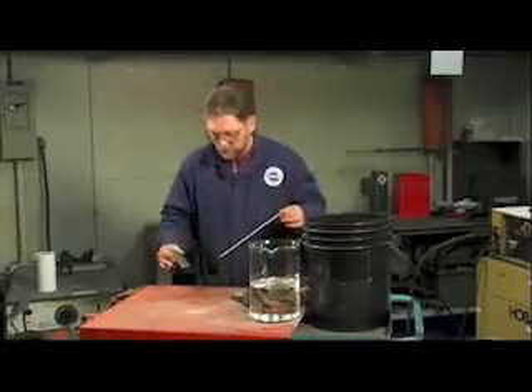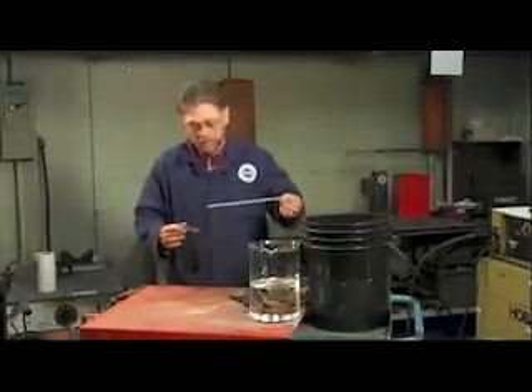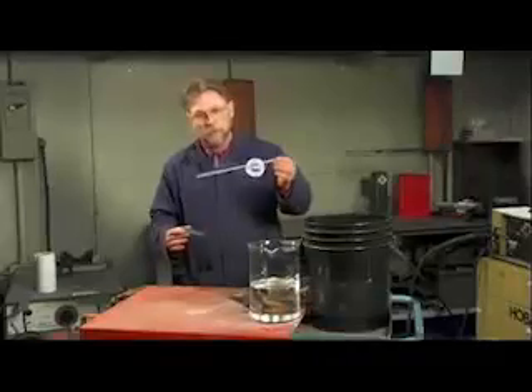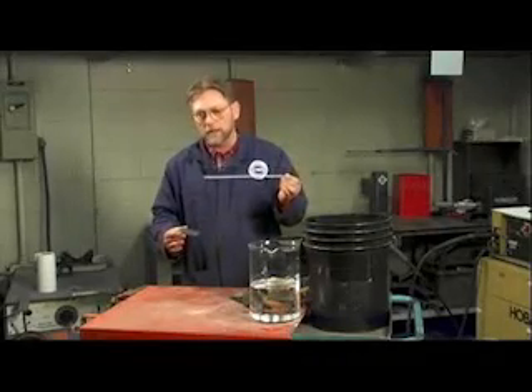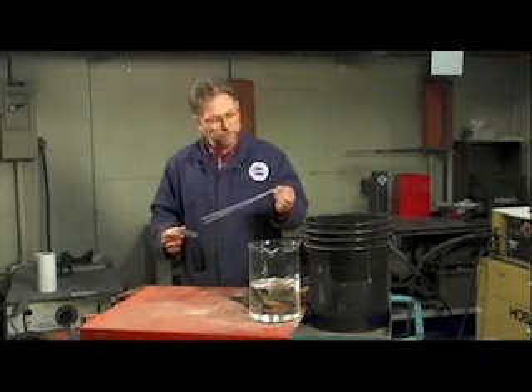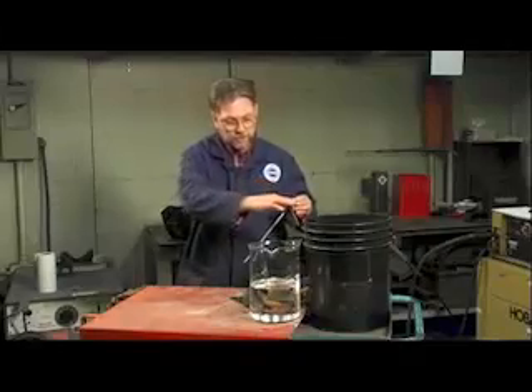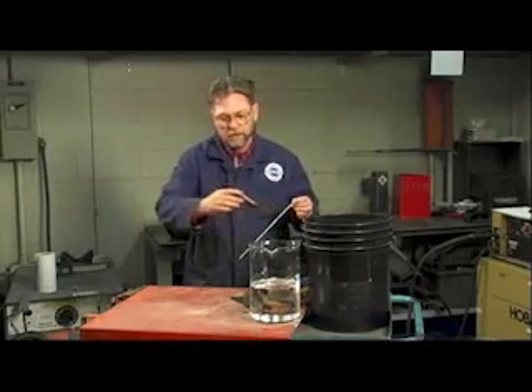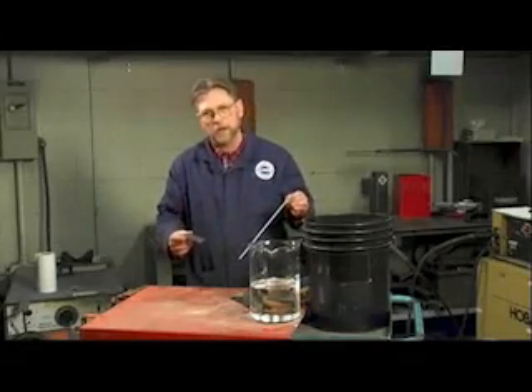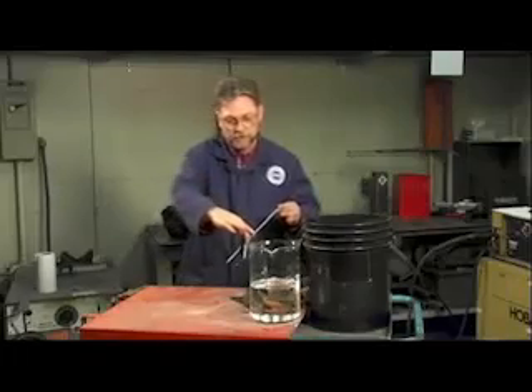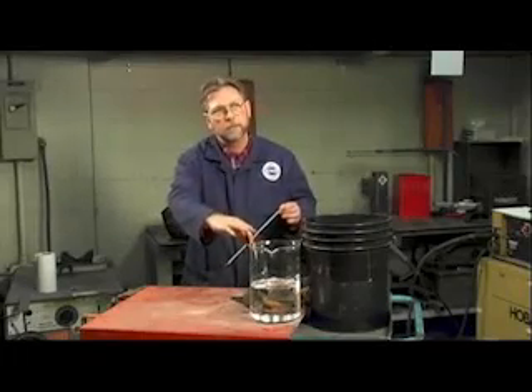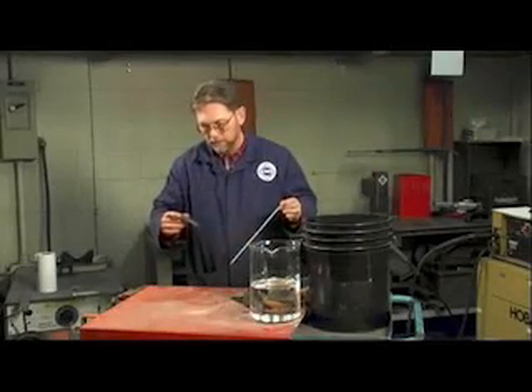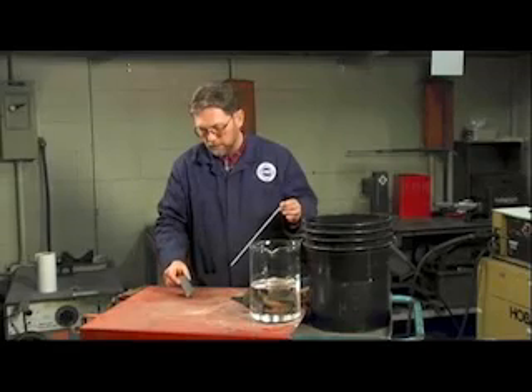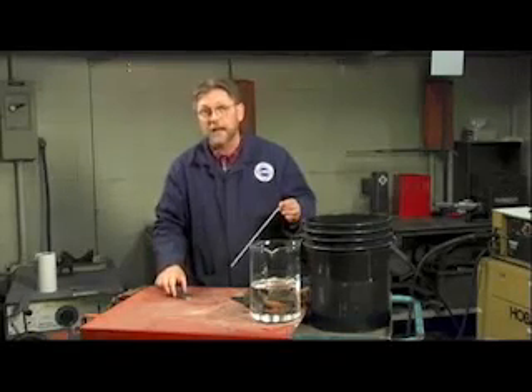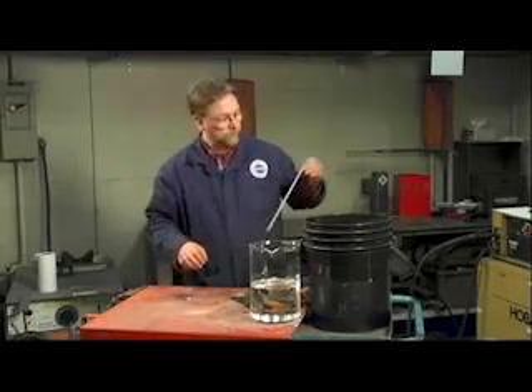So what we're going to do now is make a weld bead on the surface of this piece of plate using a 2.4 millimeter diameter low hydrogen electrode. We're going to quench it into some cold water and then dry it off, chip the slag off of it, and immerse it in this beaker of light oil. And you'll be able to see that there will be very little, if any, gas at all that comes out of that bead.